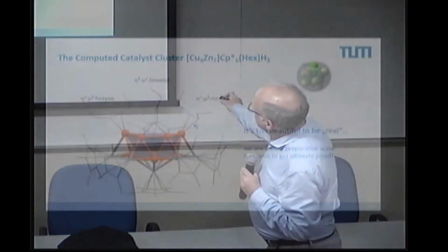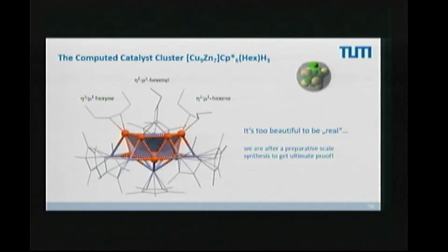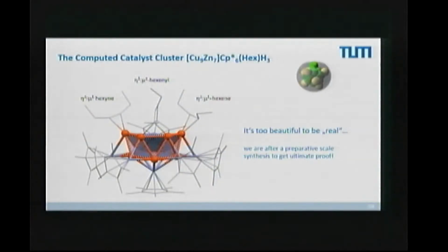So this is exactly what we wanted to have. We have the copper inside, we have the zinc outside. This emulates a brass phase, a copper-rich brass phase, where you have a copper phase and you have a bulk which is alloyed. And this is just the hydrocarbon protective group capping, and it's exposed here for doing some chemistry with our substrates. So that would be the coordination of the parent substrate, the hexine. That would be the coordination of the hydrated one, the hexene. And this one is difficult to see. This is a carbon atom which is bridging two coppers. This is the mu2 hexenyl. There's just one hydrogen atom attached to the triple bond. It's just too beautiful to be true.